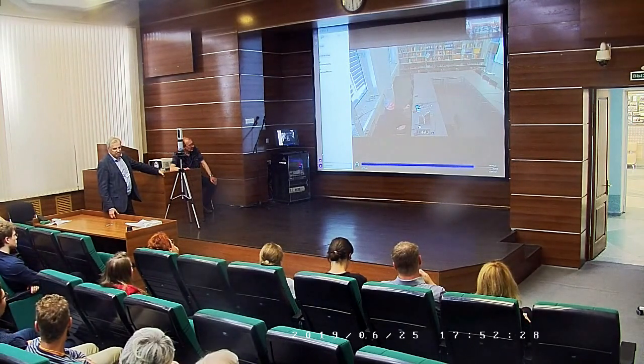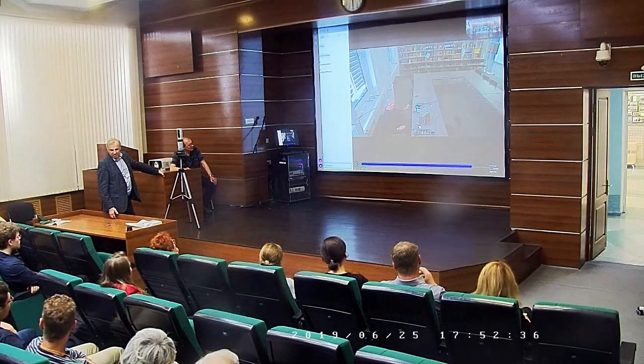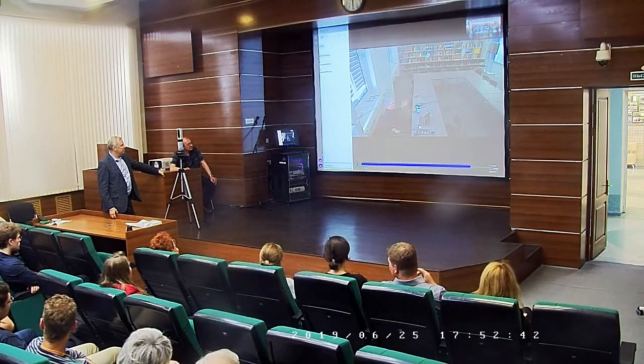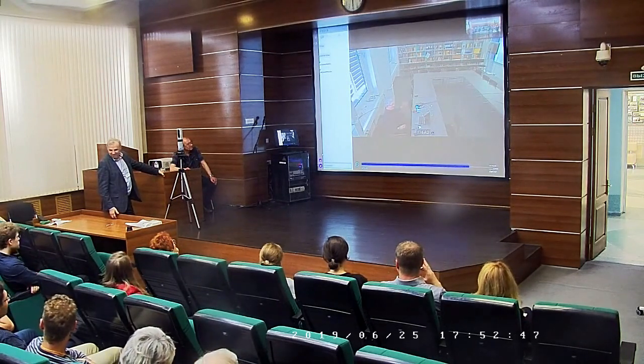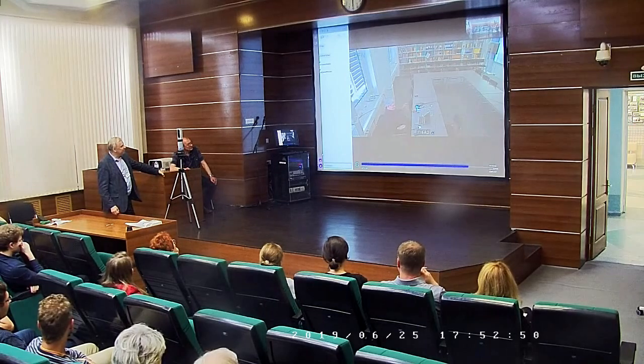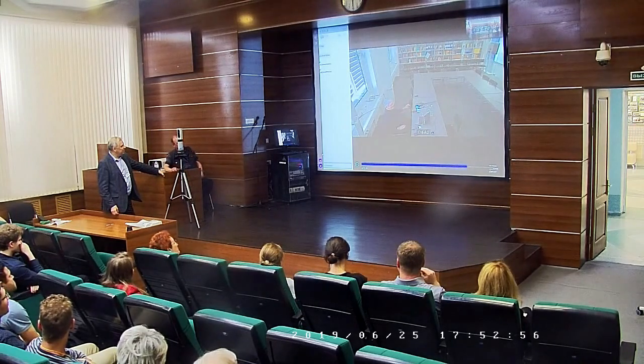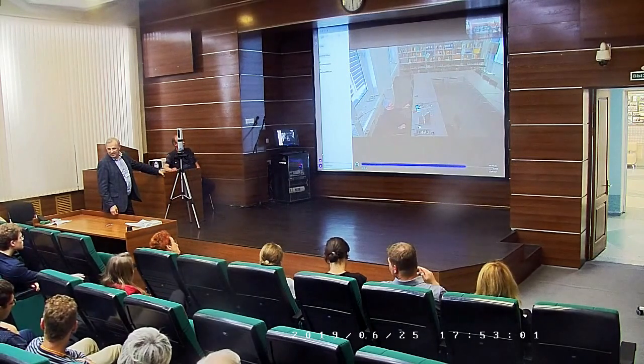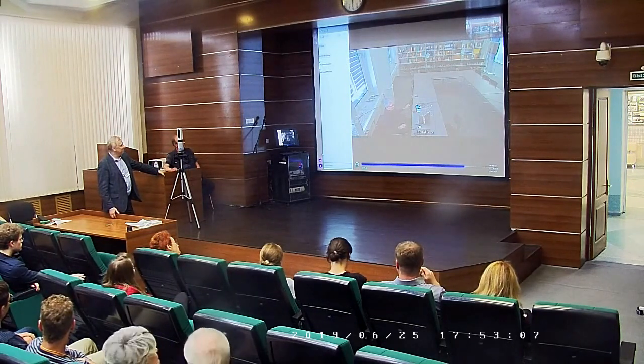So at the moment we are finding out how much this damage is. I can tell you we have operated the electrolyzer that you see now for a little over 6 months in intermittent operation, and we did not have to change the electrodes yet. But of course 6 months is nothing. You would expect 6 to 7 years of lifetime, and we're looking forward to seeing how long that takes. My scientific view is that there has to be damage to the system, because we understand very well that there are universal structural modifications on an electrode as a function of electrochemical potential, and if you change these, that usually leads to degradation of the material over time. So I would expect, yes, there is massive damage.